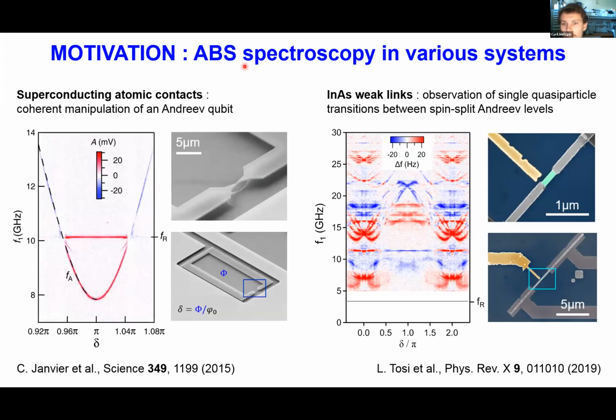This has been used in various systems to probe the Andreev spectrum. So, for example, in one atom contact between superconducting electrodes, it has been possible to study the short junction physics and to probe the coherence of the so-called Andreev qubit. And more recently, in indium arsenide weak links, we have been able to observe these single quasi-particle transitions that I was mentioning, and that are a signature of the spin-split nature of the underlying Andreev levels. So in both cases, using the circuit QED toolbox, we have been able to probe the Andreev spectrum.